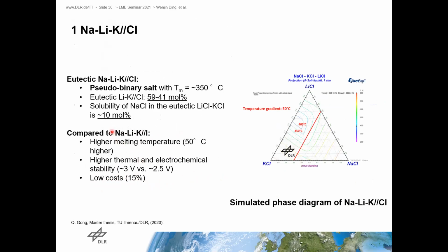Then we studied the chloride salt systems. Compared to the iodide, it has a little bit higher melting temperature, about 50 degrees higher, and the properties are similar to the iodide.